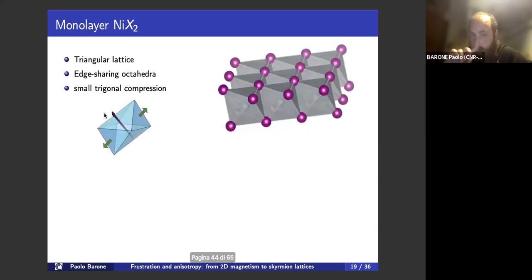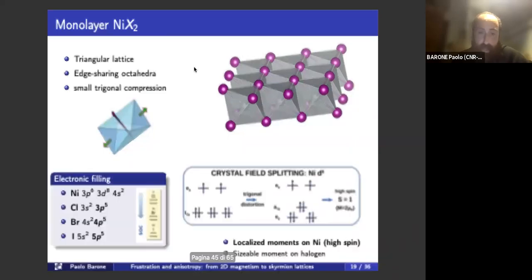So instead of looking at the bulk, we wanted to study the two-dimensional magnetism. So we focused on just the monolayer. As I said before, the monolayer is a triangular lattice of edge-sharing octahedra. There is a small trigonal compression along the direction perpendicular to the layer.